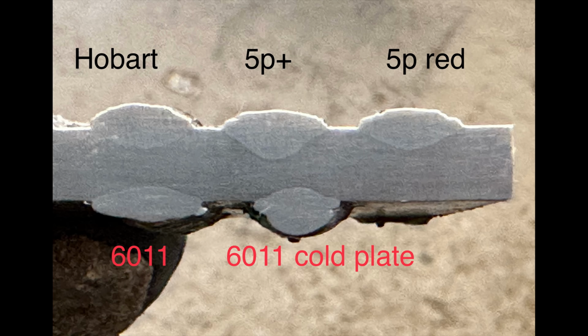Now the 6011, that's a different story. You can see the first pass was cold, humped up, no penetration. And in the second pass on a hotter plate, significantly more penetration overall, but nowhere near what the 6010 is. Now there's a couple reasons for that. One, I find that 6011 needs more amperage than 6010. So I was running it a little bit on the cold side.